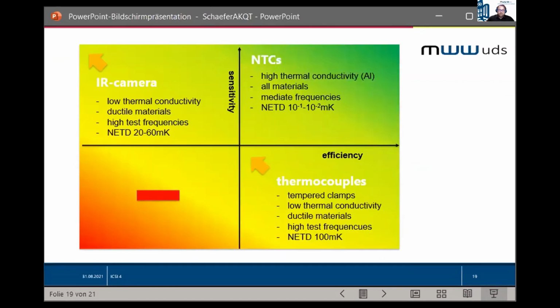So I can conclude that choosing a method is a decision of time and costs for materials with low thermal conductivity and test setups with high frequencies. You can do the measurements with thermocouples or infrared cameras, although the infrared cameras are a little bit more expensive than thermocouples. But if the material has a high thermal conductivity, such as aluminum, and the temperature profile is flat and hence hard to measure, you need NTCs. Also, if the sample is small, then less heat is generated, and if you use a servo-hydraulic testing machine, less heat is produced per second, and this makes NTCs necessary to get good and reliable results even below this knee point.